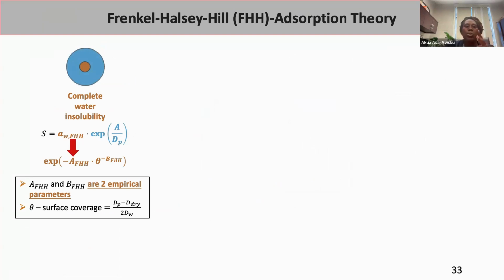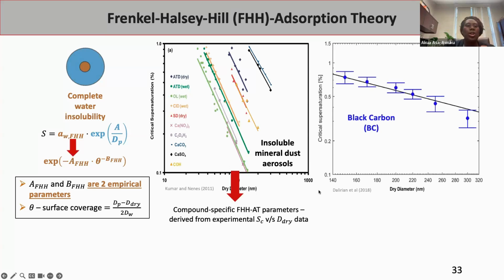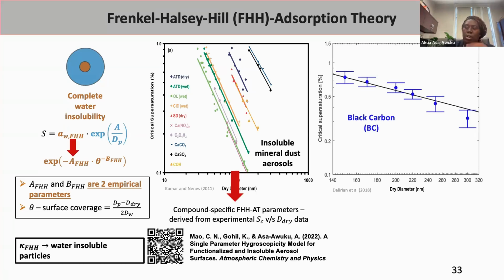Well, there's an additional theory called Frenkel-Halsey-Hill adsorption theory. It's essentially a Langmuir adsorption that says, instead of dissolving that core, water is going to condense on the surface of that core. And this Langmuir isotherm can be described by two parameters, an A-B parameter, which describes essentially the interaction from the surface to that first water vapor molecule, and also that first layer to the outer layer of the droplet, which influences how much can adsorb onto that surface. We know that this FHH theory really works well for things like mineral dust and black carbon. And there are several studies that have applied this droplet growth to insoluble aerosol. What we did earlier in this nanoplastic study is that we defined a hygroscopicity parameter based off this adsorption isotherm.